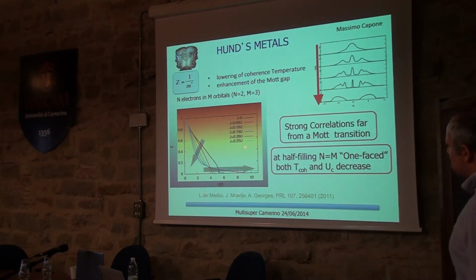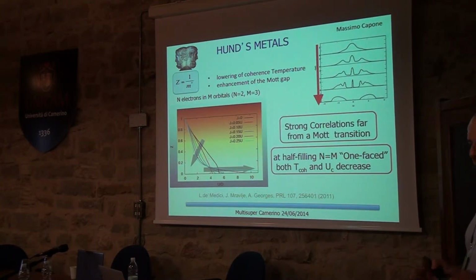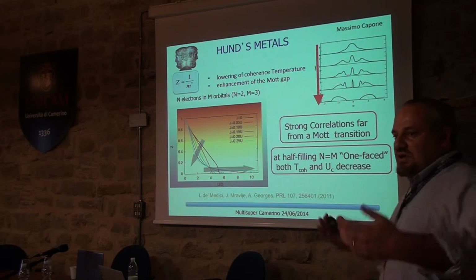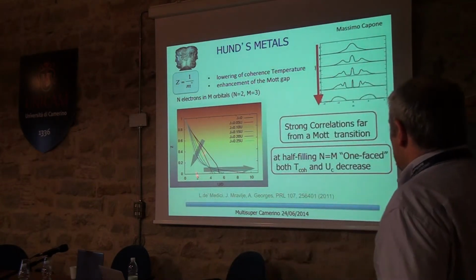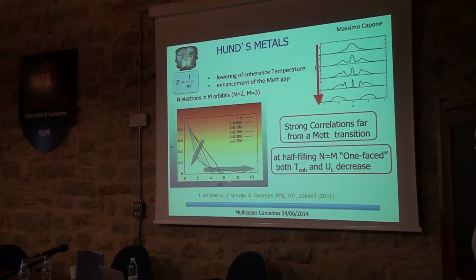When you introduce the Hund's coupling, what happens is that first you have a very rapid decay. So you need a small U to make this reasonably correlated. And then you have a flat tail, where the degree of correlation does not depend so much on U. So you clearly have a dichotomic behavior, and the Mott transition will happen eventually at some very, very large U. So you have a wide region where your system looks correlated.